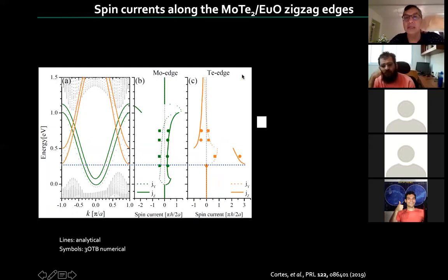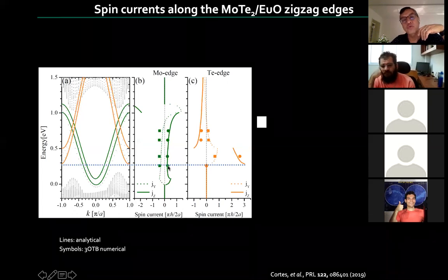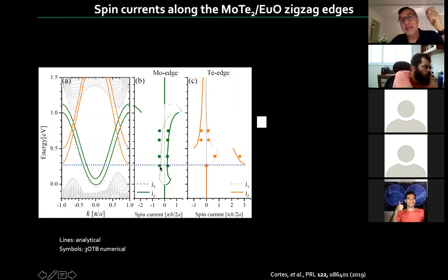Remember that there were two, the moly and the chalcogen edge. Here, the chalcogen edge, which is this orange, is not populated yet. So of course the current is zero. So all the current is on the moly edge. But as you can tell here, there are two projections, again, the Y and the Z, and so there is some current, and it has opposite sign. So the current in the Z direction is positive with some value, while the current in the Y direction, the other orientation, is negative, but the net current is the combination of the two with a tilt that depends on whichever of the two wins.